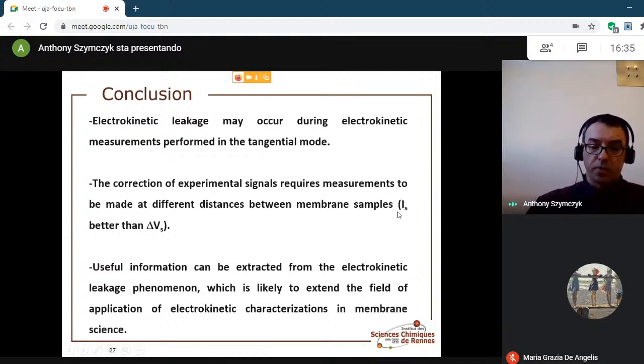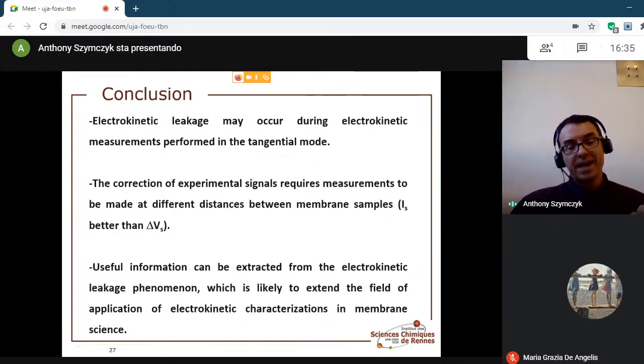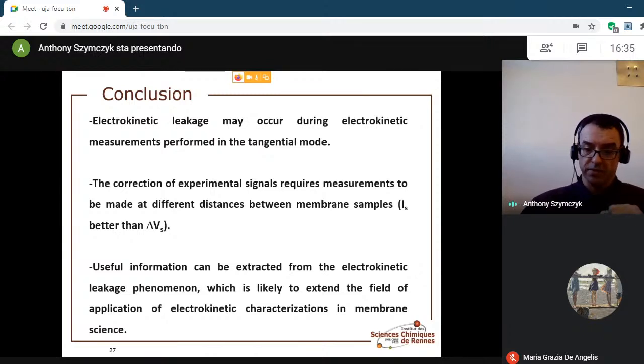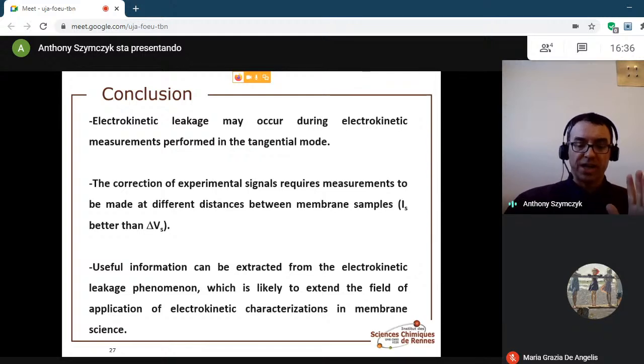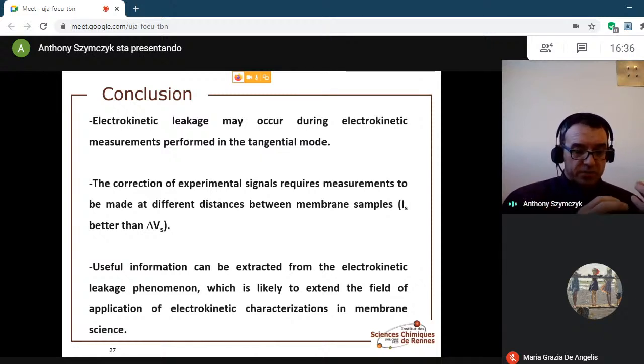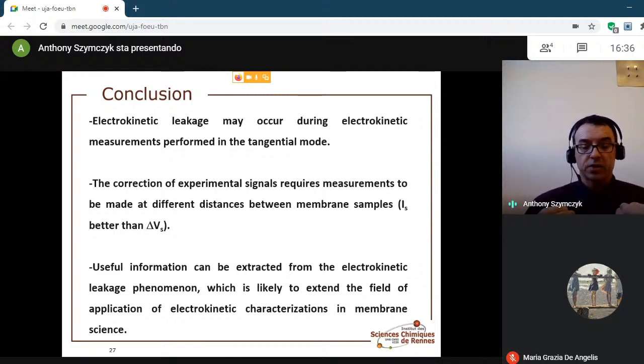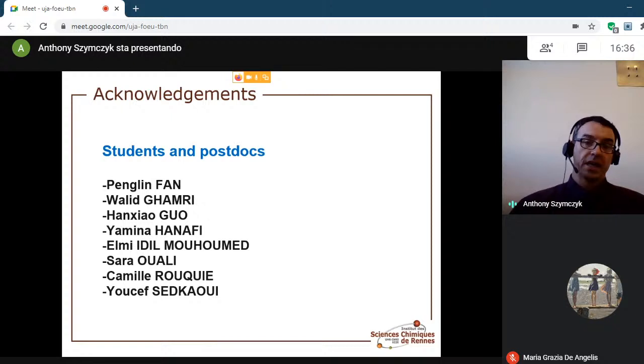I've not addressed this point specifically, but since the membrane matrix is likely to contribute to both the streaming current and the electrical conductance, it is better to use the streaming current method rather than the streaming potential method, as the combination of the two effects can lead to a nonlinear variation in the streaming potential coefficient with the distance between the membrane samples, which can make the extrapolation procedure more challenging. Eventually, knowing that the electrokinetic leakage crosses part of the membrane matrix, we have seen how to extract the information it contains and how the electrokinetic leakage phenomenon is likely to extend the field of application of electrokinetic characterizations in membrane science.